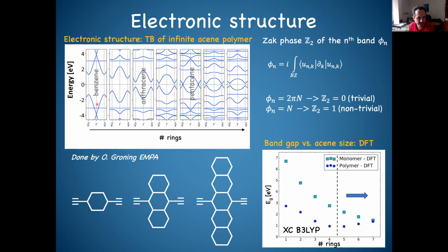For this polymer, I see that the band gap is pretty large, but when I start to increase the number of benzene units in the acene, you start to see that the band gap is closing. For pentacene, for example, we choose the hoppings at a certain value and get exactly the metallic phase, and then we start to open the band gap again. If you look at the DFT calculations, where of course we had the tight-binding metallic state, you see that the trend is very similar.